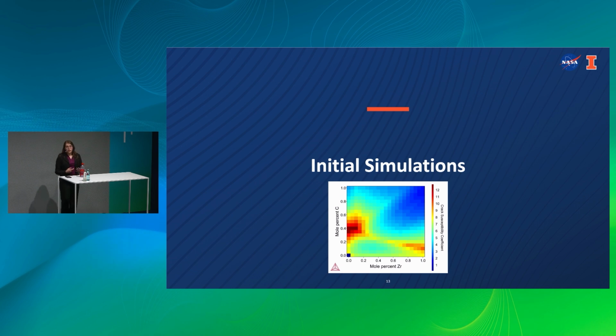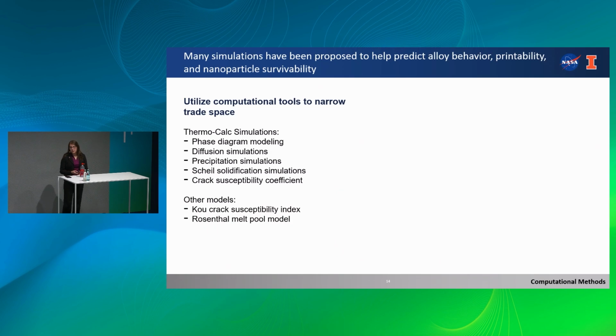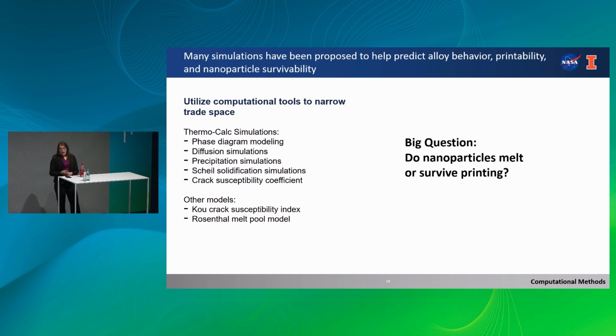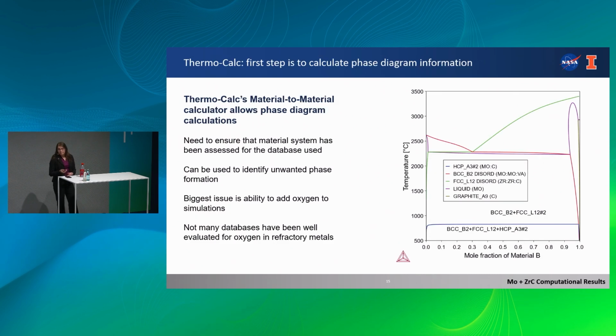So we looked at some initial simulations. A lot of the work thus far, we've used kind of traditional welding simulations. So you can use a variety of tools. Mainly, we've looked at using a lot of Thermo-Calc as well as traditional weld models. So with Thermo-Calc, you can use things such as phase diagram modeling, diffusion simulations, and Scheil solidification simulations, which are very commonly used in additive manufacturing to predict crack susceptibility, and different things like that. And one thing that we've tried to predict is, do these nanoparticles melt or survive printing, and what methods do we use to actually predict this?